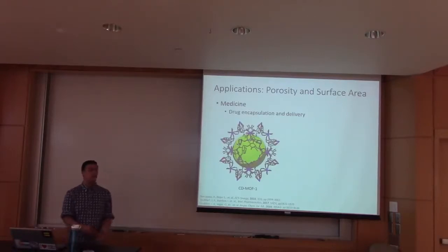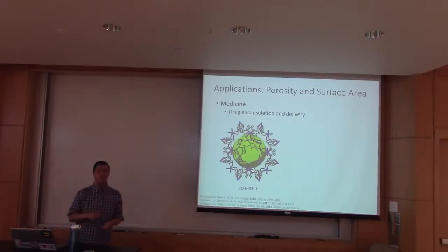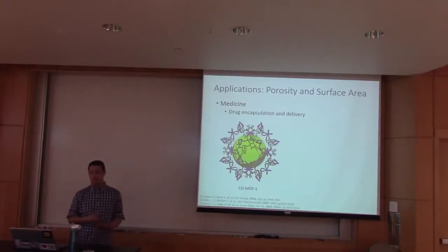And they found that when they were administering ibuprofen in the CD-MOF, the blood plasma levels of ibuprofen reached the same concentrations at the same time as our everyday ibuprofen salt, but the half-life of the ibuprofen drug was actually increased by 100%. So rather than taking the drug that we have normally over the counter, where it's just the salt, you can actually, instead of taking it every 4 to 6 hours, if you have it encapsulated in a CD-MOF, take it every 8 to 12 hours, which has very big precedence in terms of future research with drug delivery.